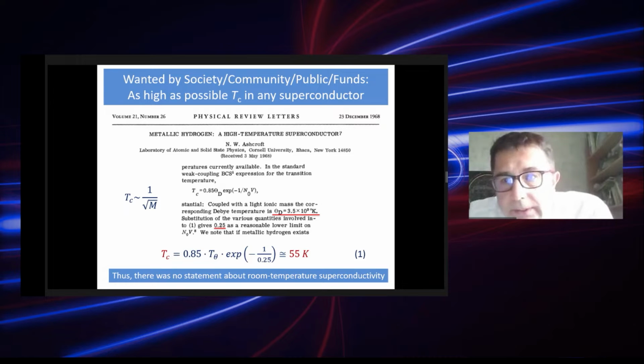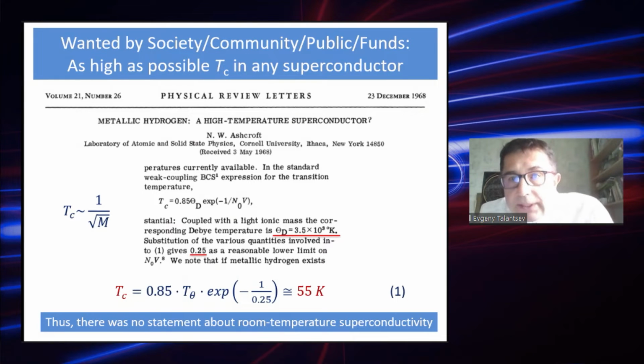It took about 11 years until Neil Ashcroft realized that Tc depends on the square root of the mass of the ion of the metal. So hydrogen, the lightest element in the universe, should actually have the highest transition temperature. And if hydrogen is metallized at high pressure, it should potentially have the highest transition temperature. Here, let's stay at that stage and actually calculate, because Neil Ashcroft provided an estimate for the Debye temperature and for other parameters in that simple equation.